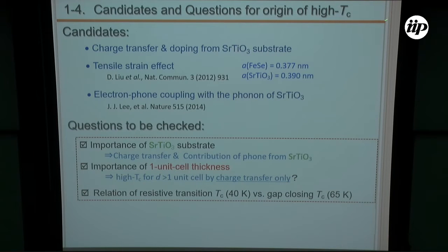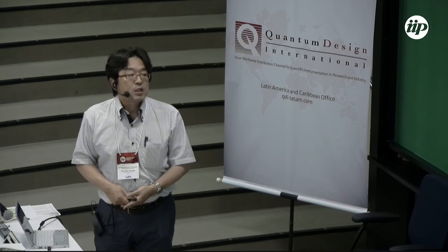Okay, as the origin of the high temperature superconductivity, charge transfer from the substrate, tensile strain effect, and electron-phonon coupling with the high-frequency phonon of the strontium titanate have been proposed. All of these candidates are based on the characteristics of strontium titanate, which seems natural, so strontium titanate has been believed to be a special substrate until our experiment. However, in order to find the essential conditions for high TC superconductivity, we should check the importance of the strontium titanate, the importance of the one-unit-cell thickness, and the relationship between the resistive transition TC and the gap closing temperature.